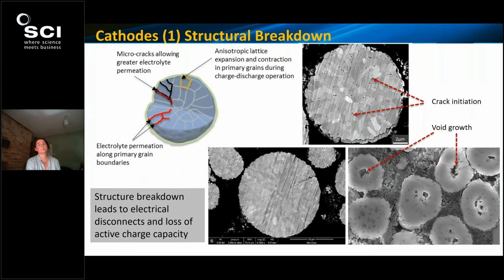Okay, so first of all, cathodes are typically based on transition metal oxides of a number of different crystalline structures and chemistries. So firstly, structural breakdown as a function of aging is a common cause of degradation in cathodes. So these materials you can see here, the image in the top right is a cross-section SEM image through nickel, manganese, cobalt, or a high nickel version, NMC811. And this is a several micron scale aggregate of lots of little nanograins, and it's very polycrystalline.